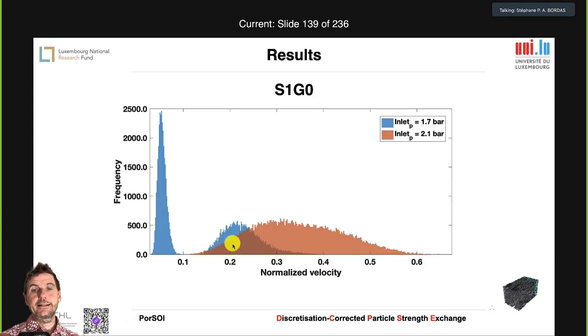And now if we look at the actual results, we see something which is very exciting. Because why? We look at the frequency of the normalized velocity in the pores. So we take the velocity in all the pores and we plot the number of times we measure this velocity using CFD. We are solving everything using CFD here, using a DCPSE, mesh-free particle method, and we are looking at the normalized velocity. So for example, if we take the value of velocity 0.05 here, in the first case where we have 1.7 bars, which is relatively low pressure, we have quite a high number of